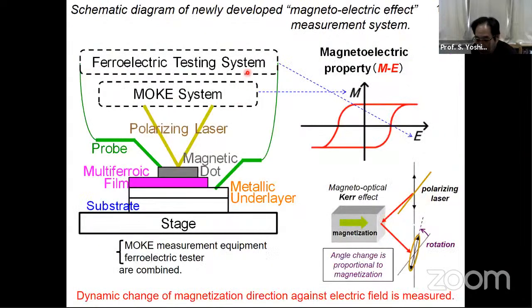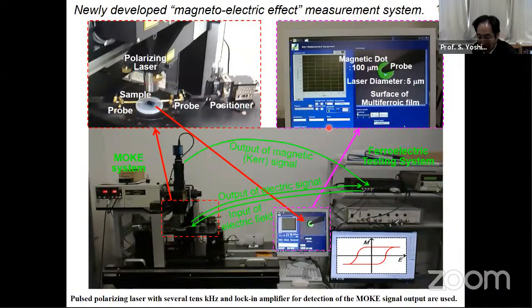So I newly developed the magnetoelectric effect measurement system. I combined the magneto-optical Kerr effect system and ferroelectric testing system like this. By using this system, we can measure the magnetization direction while applying the electric field. So the dynamic change of the magnetization direction against the electric field will be measured. These are the pictures of the new system.